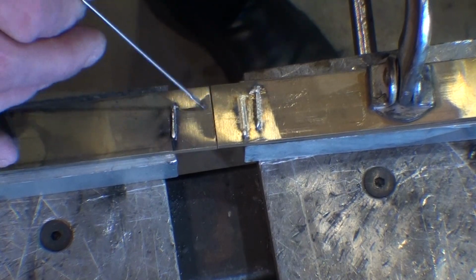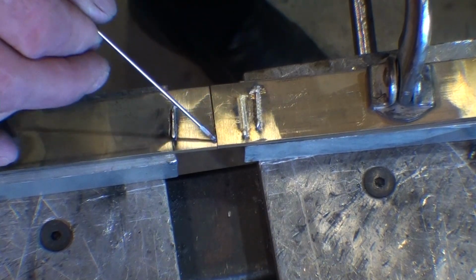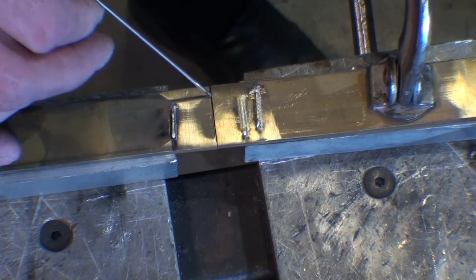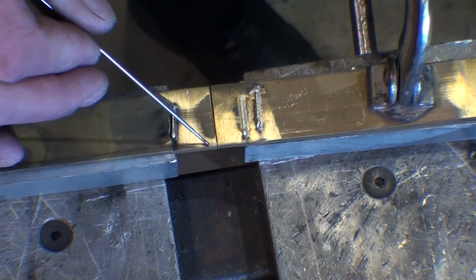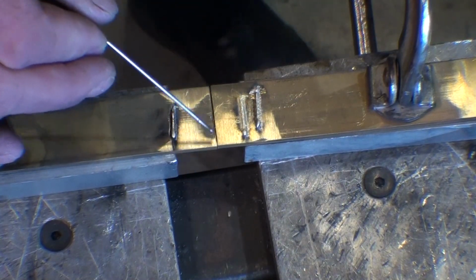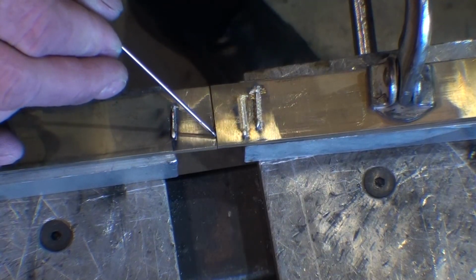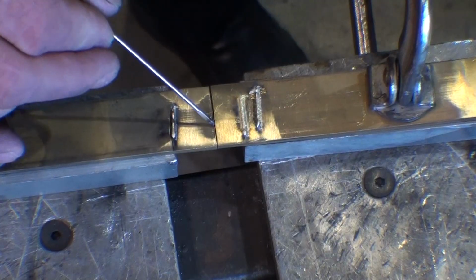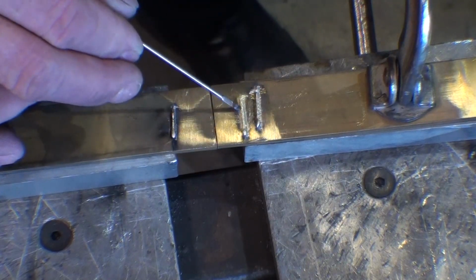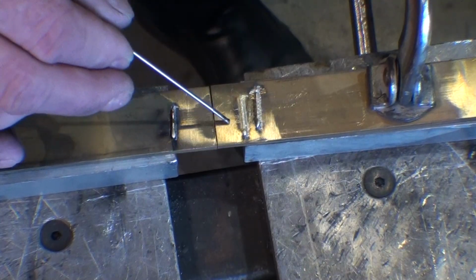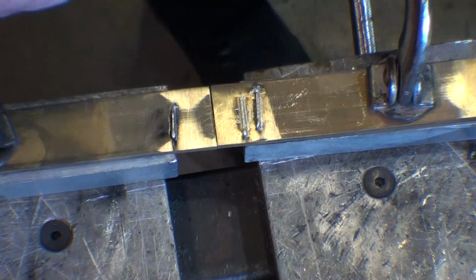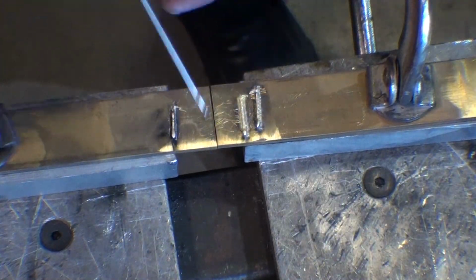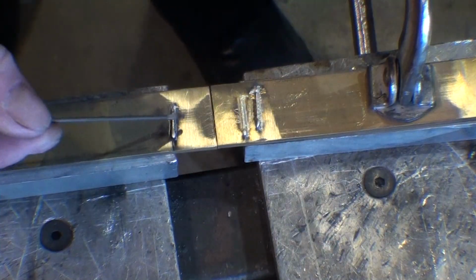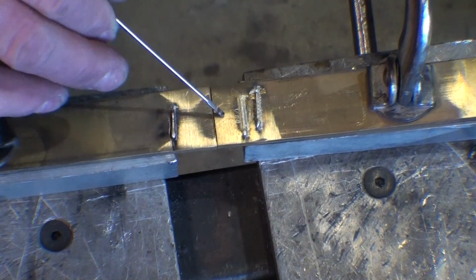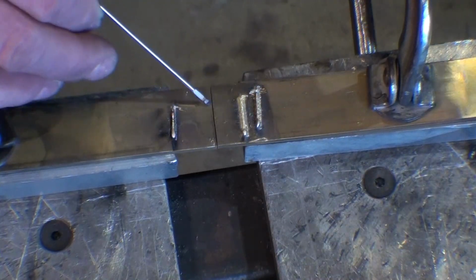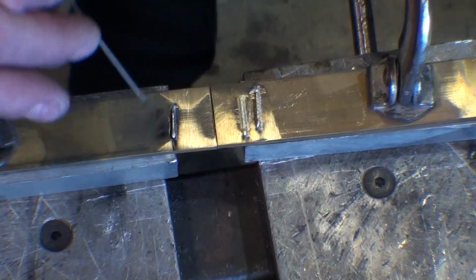So basically it's gonna melt the two pieces of material on the surface. It's gonna have almost zero penetration. Then we're gonna do it on the other side as well, and we're gonna break it up. So it's gonna be somewhat strong. How strong? Let's say if you have some appliances and it's just for visual, you could do this, and then you can grind off the excess, and you still have a 0.5 millimeter filler metal flow into your gaps. I don't think more. Same thing from the other side in that case. So basically you end up with approximately 1 millimeter fusion and 2 millimeter gap, because it's a 3 millimeter material.